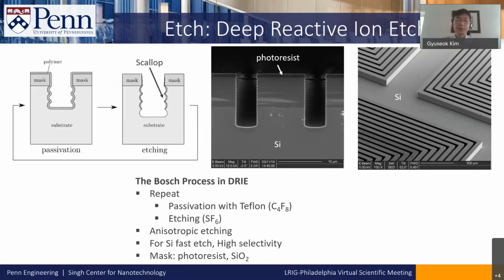This is an interesting tool. The process in this tool consists of two steps. One is passivation, and the other one is etch. First, the tool protects the material with Teflon, C4F8, as you can see on the left side of the figure. And then the tool etches the material with SF6. Of course, SF6 etches Teflon a little bit. Each etch step is an isotropic etch, but the tool repeats this passivation and etch step again and again. And eventually, we end up having an anisotropic etch profile.